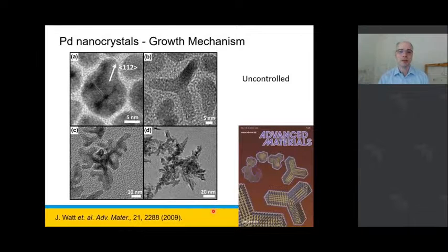And this was making some branched palladium structures. The way we could make these branched palladium structures was essentially by controlling the growth kinetics of the system. In this reaction with these palladium structures, the reaction was essentially uncontrolled, and it was going quicker and quicker and quicker until at the end of the reaction, the decomposition of the palladium precursor was going really, really super fast. So we were ending up with a lot of dendritic growth and dendritic structures at the end.